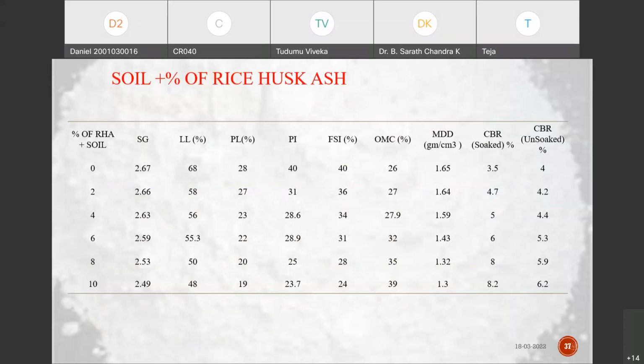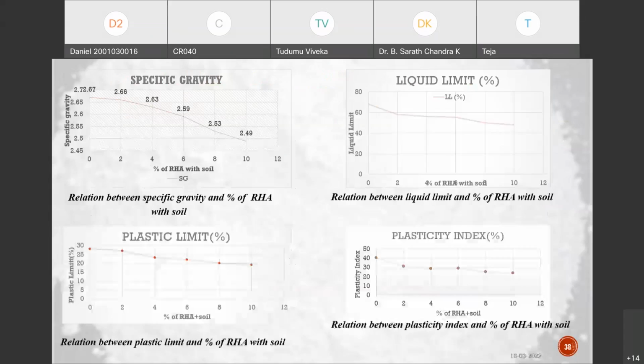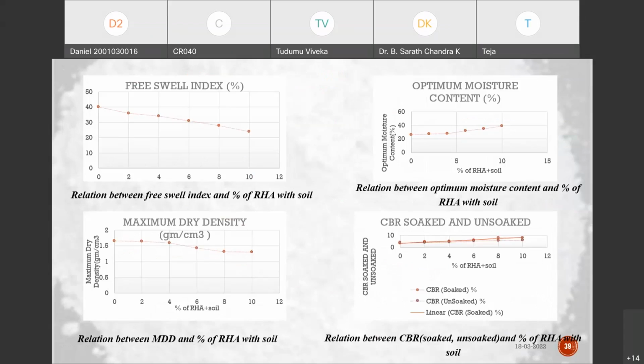The rice husk ash is 0, 2, 4, 6, 8, and 10%. So these are the results that were obtained. If we see the graphs, the relation between specific gravity and the percentage of RHA with soil, and liquid limit, plastic limit, and plasticity index, these four are reducing with respect to the increase in the percentage of the RHA. And if we see here, free swell index and maximum dry density are also decreasing with respect to the increase in the RHA, and optimum moisture content and CBR are increasing with respect to the increase in the percentage of RHA and soil.